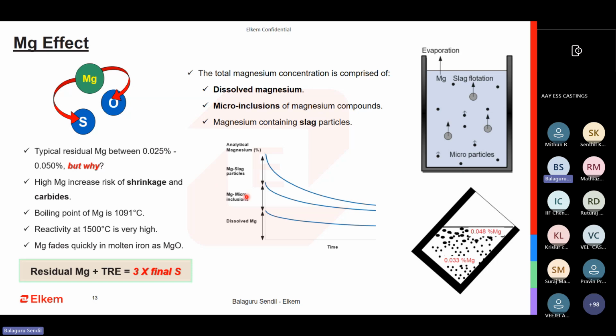And then you have magnesium which is actually forming these micro inclusions, which is in this particular area of the graph. These are very small, 1 micron, 2 micron. This is basically MgS, magnesium sulfide, and magnesium nitride nuclei, very small, very stable. And then we also have magnesium which is free, MgO-based slag flotation.